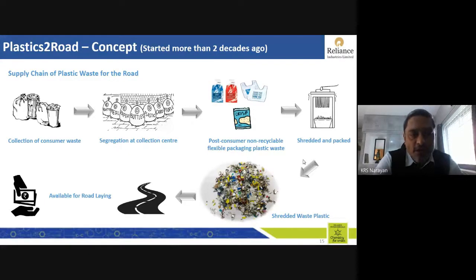So the concept is you have to find a supply chain for waste plastic to roads, then segregation of the collection. Very, very important to segregate these materials. So we are only interested in these carry bags and the multi-layered films, which provide end-of-life solutions. And these post-consumer, non-recyclable, flexible plastic is then collected. Then they are sent to shredding as per the sizes prescribed by the IRC code. They are shredded, and then these shredded materials are mixed with the hot aggregates, and later the plastic coated aggregates are mixed with the bitumen, and the road is laid as per the conventional process. So this is the concept of plastic to road, which has been prevalent for the last 20 years, more than 20 years in India.